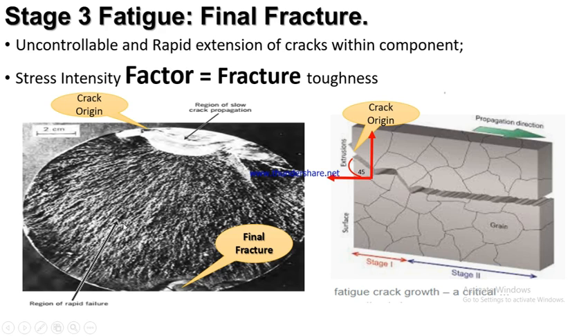You can see from this fracture surface of a material, at this particular place, like I told you, there is no striation occurring at the surface of the material. So you can see the crack initiated from this particular place, and finally this is the place where there is what we call a region of rapid crack propagation or rapid failure, and finally the fracture took place at this particular zone. You can see there's no striation here.